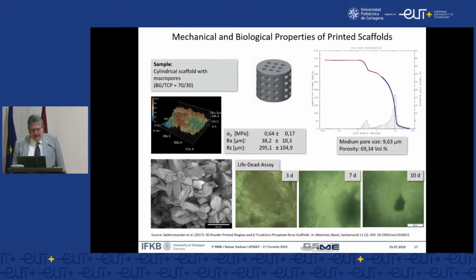another response in the so-called reference fluid, where you have stem cell solutions, stem cells of a special type that are used and can be made visible by a contrast additive. The question was, some of these materials, you know from the mineral composition, have a certain basicity. They have a pH of more than 10. And this is not beneficial for a sensitive cell culture. Or on the other side, it can be on the acidic side. It's also crucial.